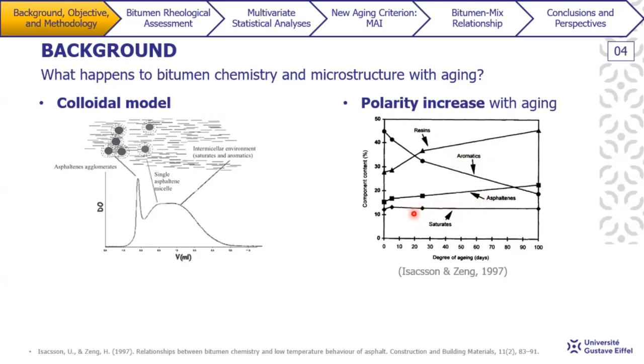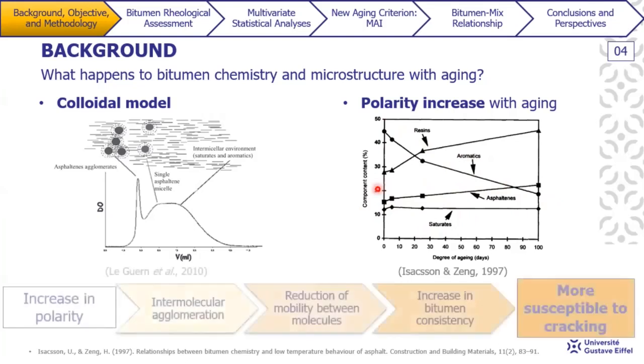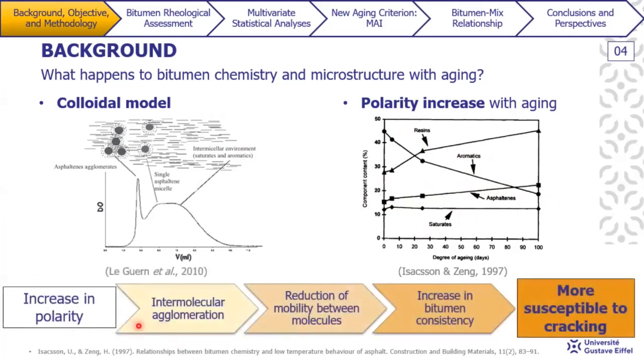And we observe an overall increase in polarity, as non-polar saturates remain unchanged with aging. We have a reduction in lower polar aromatics, while we have an increase of the most polar fractions, resins and asphaltenes, with aging. So the increased polarity will favor the intermolecular agglomeration, especially of the heavy ones such as the asphaltenes, like the ones that we see here, the agglomeration of asphaltenes, which will reduce the mobility between molecules. And this will lead to an increase in bitumen consistency, to the detriment of bitumen's ability to disperse stress. And consequently, we're going to have a bitumen that is now more prone to cracking.